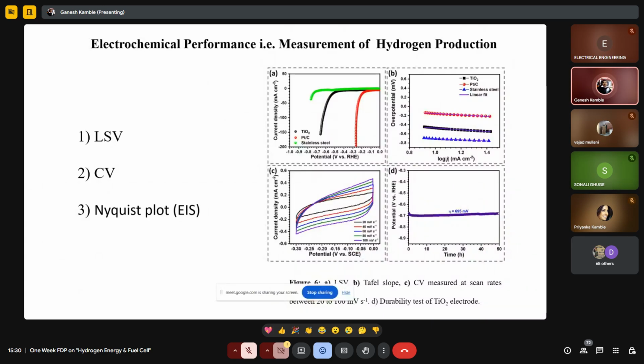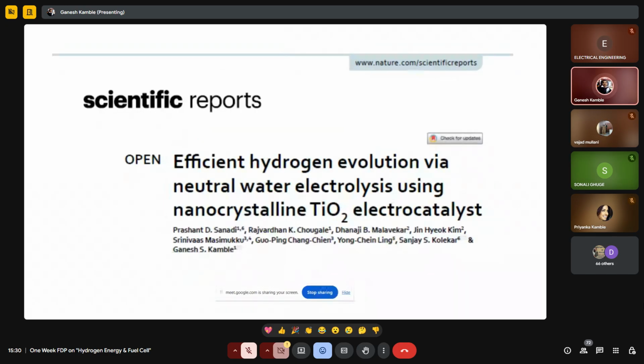Generally, platinum or noble metals are nowadays used as electrocatalysts, such as platinum, rhodium, gold nanoparticles, silver nanoparticles, or mixed nanoparticles. But they are rare elements, and the cost of the catalyst is very high. That is why researchers focus on metal oxides, mixed metal oxides, or nanocomposite materials as electrocatalysts. TiO2 is one of them, as is ZnO. These types of catalysts are nowadays used for water splitting technology. The electrochemical performance was checked by LSV, CV, and Nyquist plot, and this work has been published in Scientific Reports.